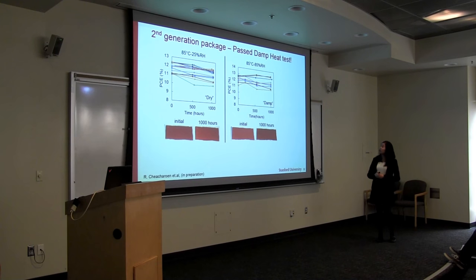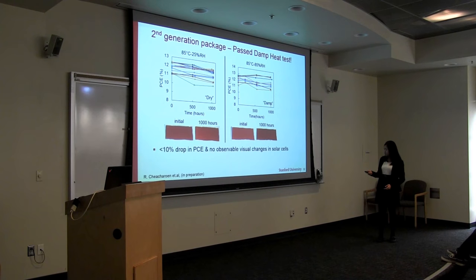And as expected, when I put my packaged solar cell with the right encapsulant and right design, it passed. Let's look at the performance over 1,000 hours. They all stay flat and have less than 10% drop in performance in 1,000 hours, and they didn't have any change in color in both cases. As I say, we passed the damp heat test, which makes us really relieved in the perovskite community.